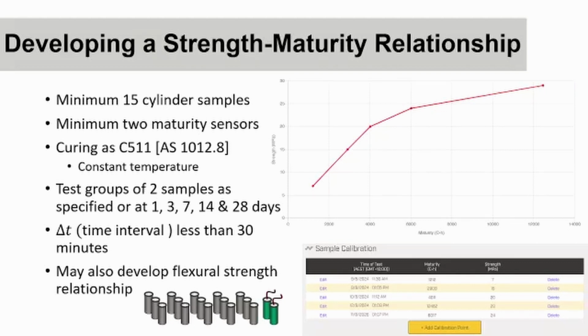So this is an example of building a concrete maturity strength relationship. A minimum of 15 cylinder samples are prepared. So you see there's 15 prepared here, and they're breaking them across 5 moments in time: 1, 3, 7, 14 and 28 days. The American Standard defines that you cure to C511, another American Standard. AS 1012.8 is similar, providing defined curing environments. And I do want to stress that is what the standard says. It's intuitive to think, oh, we could change that, we can try and adjust temperature gain. But the raw use of the ASTM standard is to maintain standard curing conditions, and also to record temperature at an interval of 30 minutes or less. So that means that you have a sufficiently granular gain of strength.